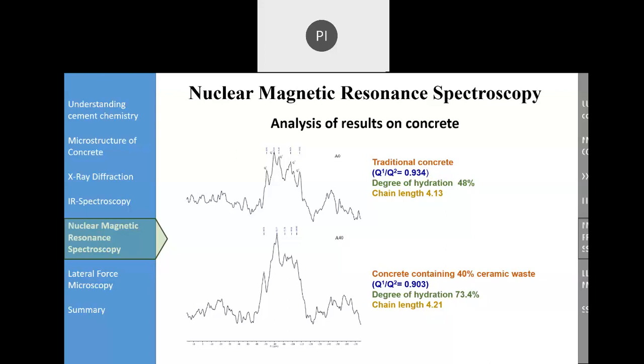And there's another term which is written here, Q1 by Q2, if you see here. So Q1 by Q2 in the first traditional concrete, say it is 0.934, and in the other concrete is 0.903. So this Q1, Q2, etc., there are different phases. So ideally, if Q2 will be more, then Q1 by Q2 will be less. So lesser value of Q1 by Q2 will mean that concrete is better, more hydration reactions have taken place, advanced stage of reaction has reached.